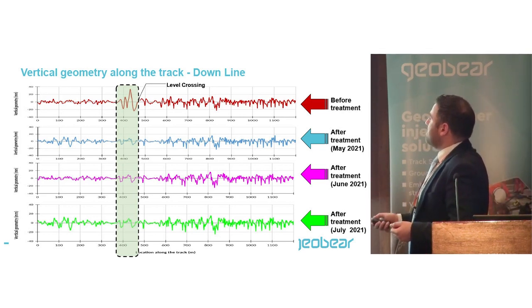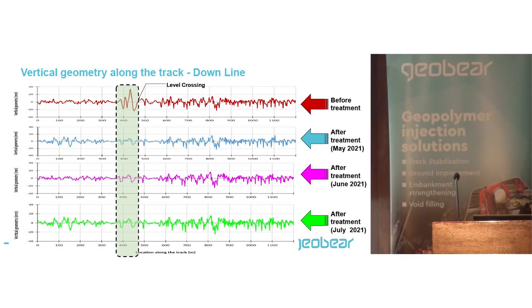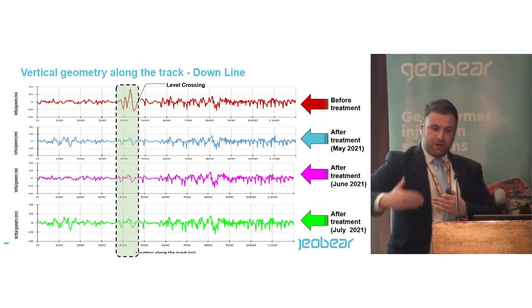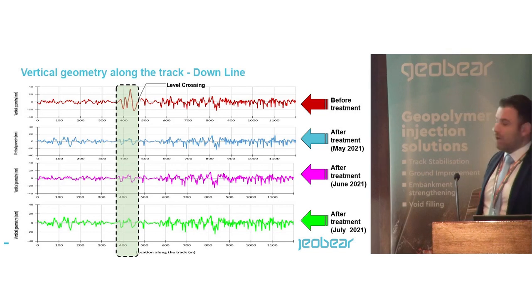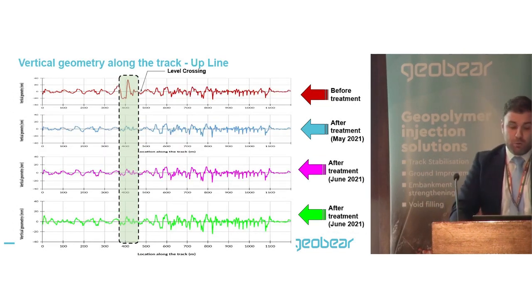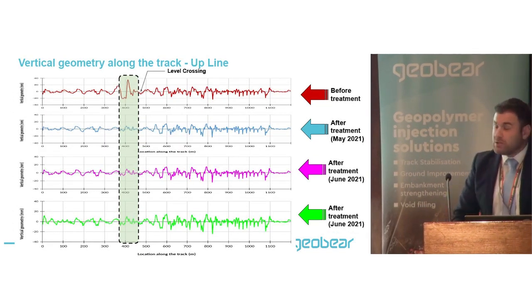And we kept monitoring it run after run for almost a period of a year. What we've done is basically looked at the biggest peak-to-peak value over run after run on both upline and downline. We compared those two, and we were seeing similar observations. And this is what we found.